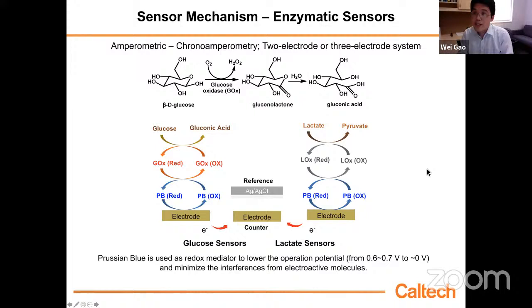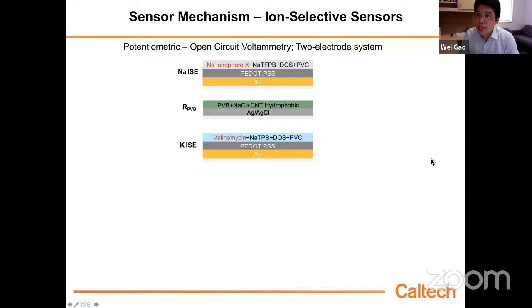If you want to detect ions such as sodium, potassium, calcium, for example, we typically use an ion selective electrode. So basically, it's a two electrode design. We have a working electrode, let's say a sodium ion selective electrode or potassium ion selective electrode. We measure the voltage difference between this working electrode and the reference electrode. On this ion selective electrode, we coat the electrode with a membrane, an ion selective membrane. A key chemical here is the ionophore. For sodium, we use sodium ionophore X. For potassium, we use valinomycin. This specific ionophore can basically introduce the selectivity here.